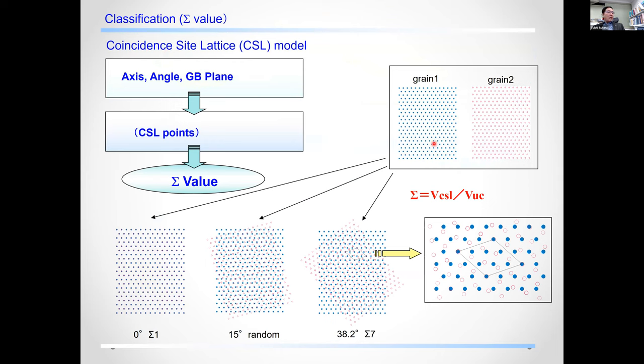So this is grain one and grain two. If grain one and grain two overlap with a misorientation angle of 0 degrees, there is no grain boundary. In this case, we call this sigma 1. If grain two is rotated by 15 degrees, a random grain boundary is formed. But if you rotate it, for example, by 38.2 degrees, the blue atoms and the red atoms overlap. In this magnified image, the blue and red atoms